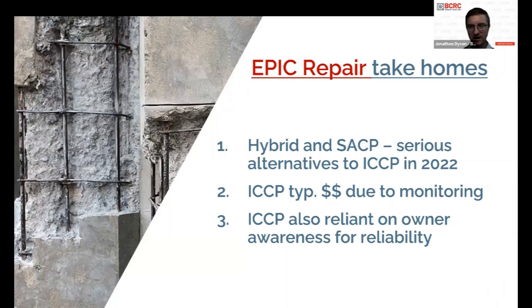So with sacrificial anode systems, they can be a set and forget sort of system where you basically put it in place and it doesn't need to be monitored. However, if it's a large cathodic protection job that is being done, it is probably still prudent to have a level of monitoring. With ICCP systems, there are some system componentry that can decrease the reliability of the systems and can fail early. And that's why that monitoring is important, to make sure that the system is still operating and providing protection. So things like the power supply, the power supply control units themselves, the reference electrodes can fail early, or they have a limited design life. All the wiring and componentry that is needed to provide that direct power supply for an impressed current system, all these things can fail prematurely and can decrease the reliability of impressed current systems.